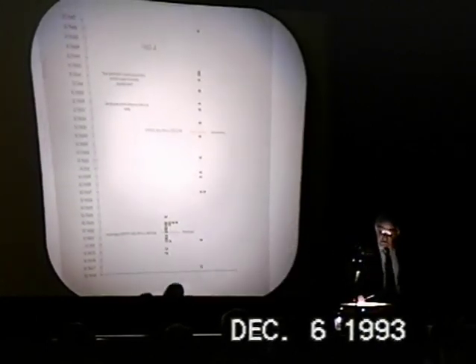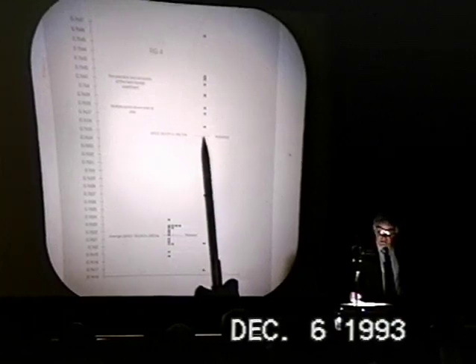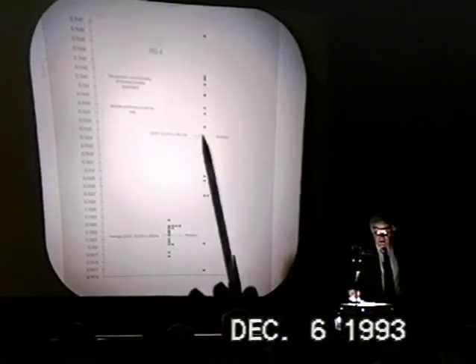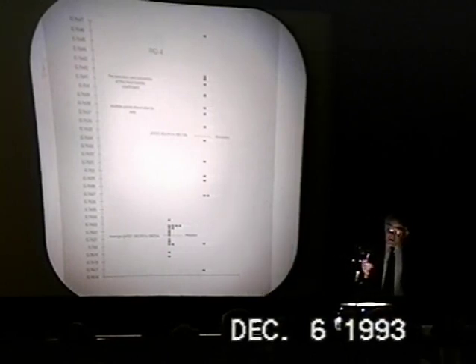And the question is, what will we in fact find? Well, for blind experiments, this was already presented last year, we do in fact find that the precision is very high, about 1 part in 10 to the 4. The accuracy is about 1 part in 10 to the 3. This is an enormous scale here of the heat transfer coefficient. And the precise value is about 1 sigma of the accurate value. So you might not think that this is significant, but the accurate value is always slightly above the precise value. And that tells us that there is indeed, for blank experiments, a small parasitic excess generation of enthalpy. It's of the order of 1 milliwatt. But this calibration of the system does in fact give us immediately an estimate of any such parasitic terms.